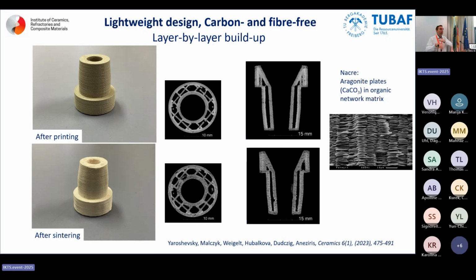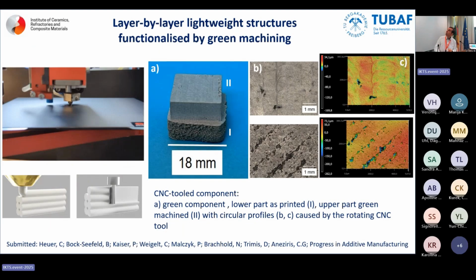In the other way, we have a filament, layer by layer, and this is something like the aragonite structure. And if I can also make microcracks, as we know from flame spraying processing, I have excellent thermal shock performance. Today the printer guys can print pore structure, and then you can also machine in green stage. So you have the porosity where you would like to have it, and you can close the pores via machining. And high speed.